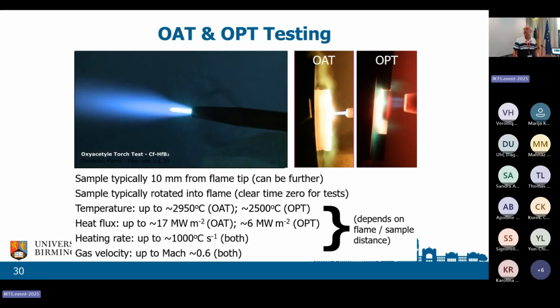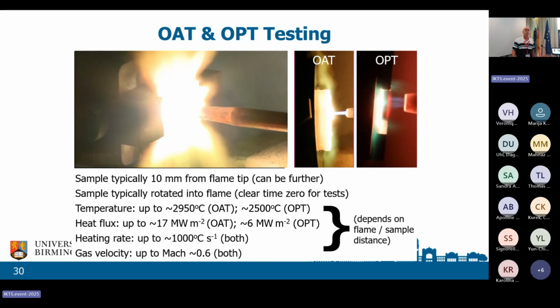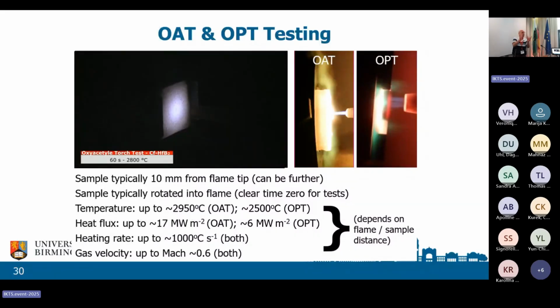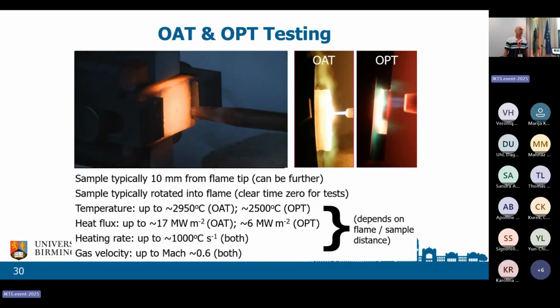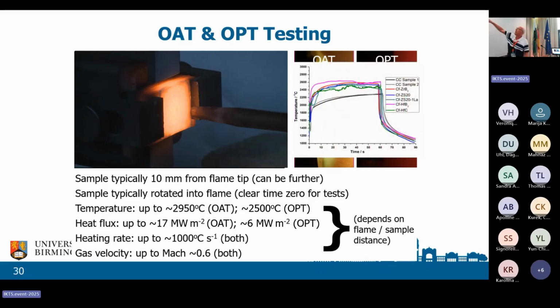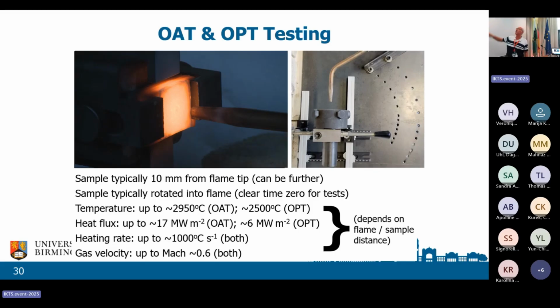And then this is an actual test. We have a filter, so we can actually watch what's happening on the surface while we're testing. The slowest part of the test is waiting for the thing to cool down so you can put another sample in. So it's a test of 5 minutes, 10 minutes, half an hour, whatever you want, and then wait 4 hours for it to cool. And then these are your heating rates. As I say, 1,000 degrees a second and it holds. It's also an indication of thermal conductivity because that black line below is carbon-carbon, which has the highest thermal conductivity, so the heat is most dissipated. And you can test at an angle as well. Instead of testing everything at 90 degrees, you can test at a glancing angle, just about any angle you want.